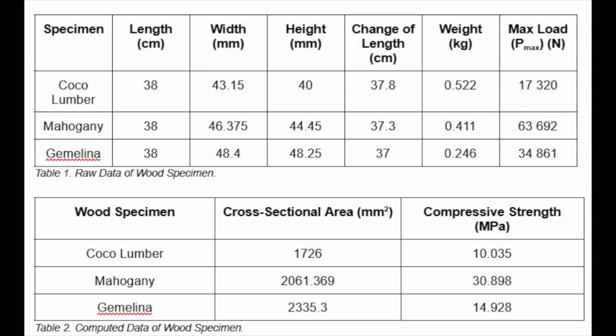Interestingly, cocoa lumber, though the heaviest, has the lowest compressive strength and the smallest cross-sectional area, 1,726 millimeters squared, indicating that higher density does not necessarily equate to greater strength. Strength depends not only on weight but also on internal properties such as grain structure, moisture content, and fiber orientation. Mahogany, with a moderate weight and a well-aligned grain, outperformed in strength despite lower mass.